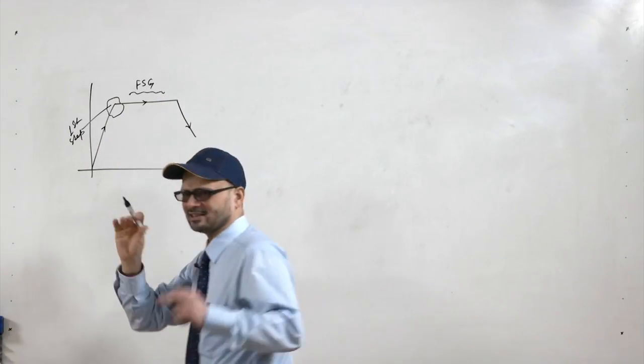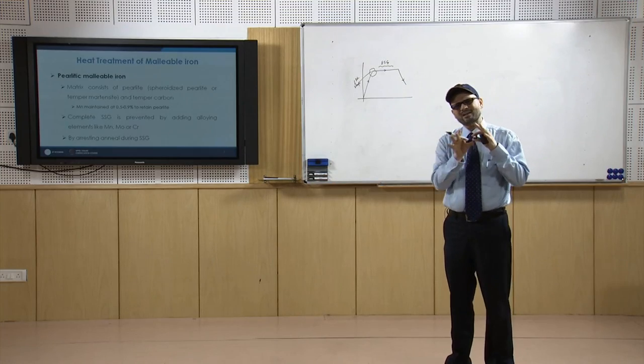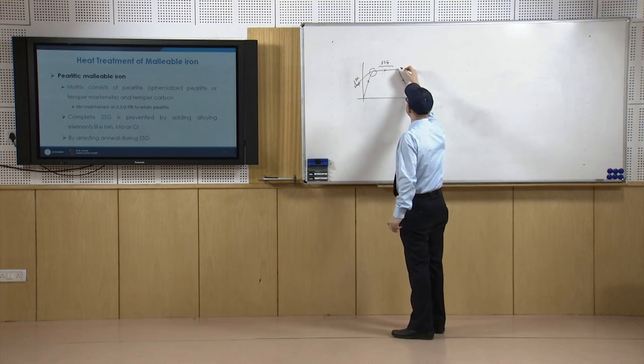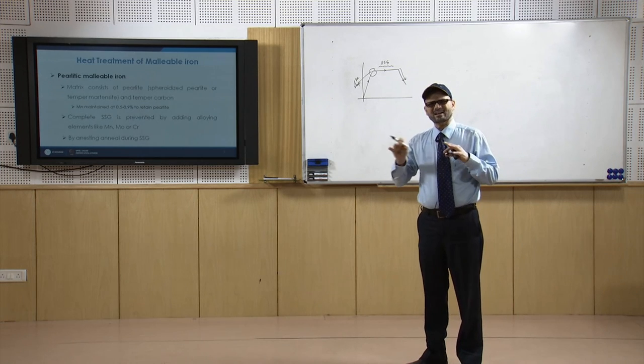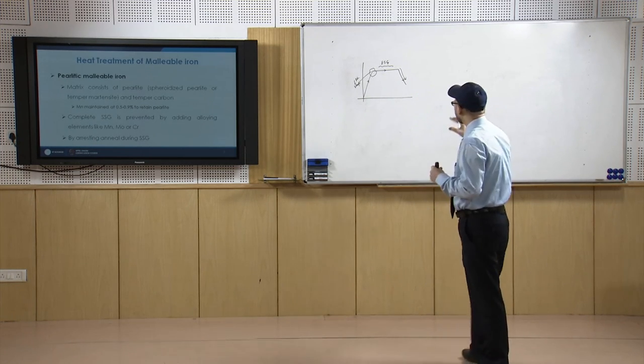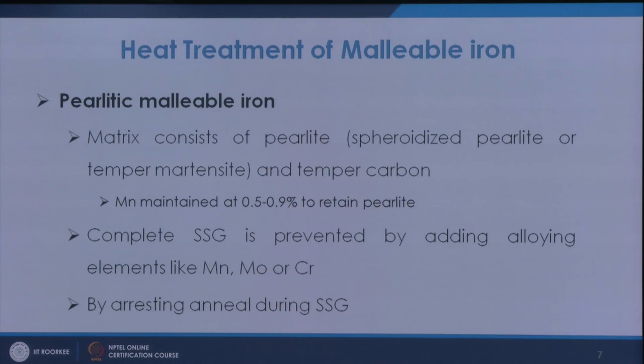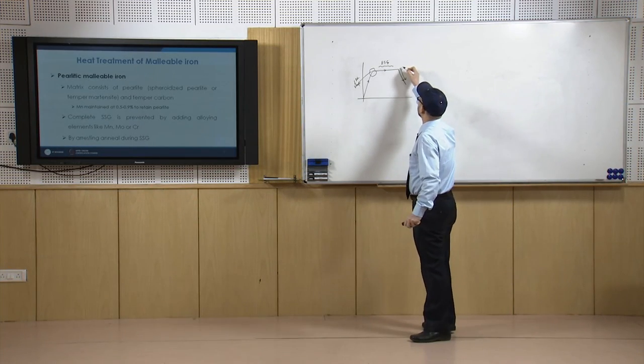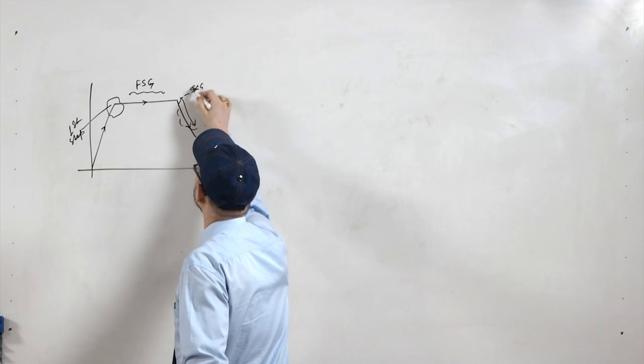In this process, in this time, all the carbides are basically dissolved and they are giving you iron plus free carbon. And then during this stage, your second stage graphitization takes place, and that further graphitization during the slow cooling basically gives you a completely ferritic structure. Now, if we want to have the matrix of pearlite, that is spheroidized pearlite or tempered martensite, and then temper carbon nodules, in those cases there are certain treatments, and for that you have to see that the second stage graphitization has to be prevented.